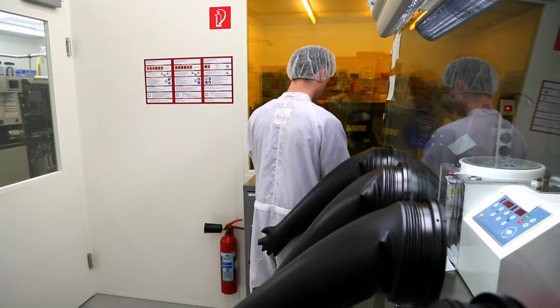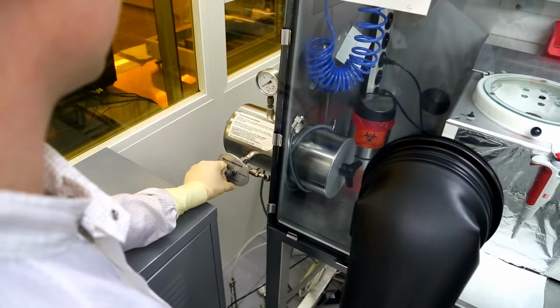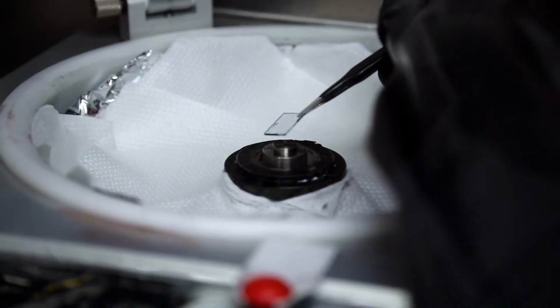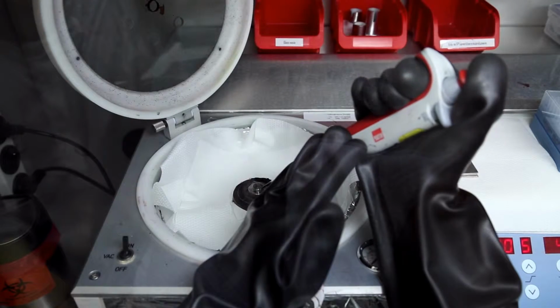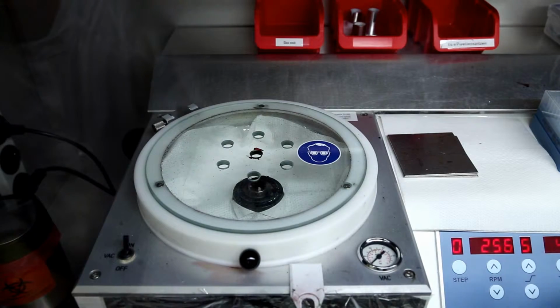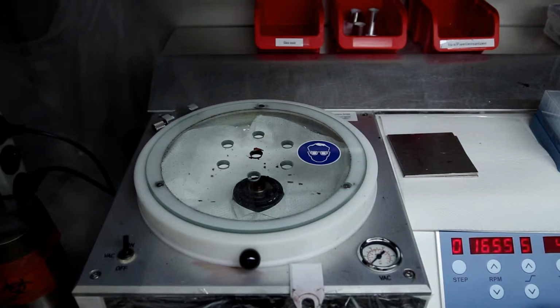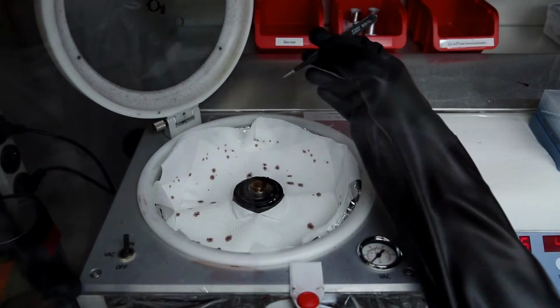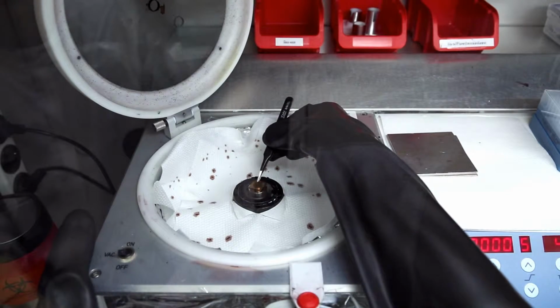The next step is the coating process, which is performed in another glove box. Once again, the vial and the glass plates must pass through an airlock and are then processed further in the nitrogen atmosphere. Daniel Baru dispenses the organic semiconductor onto the glass plate by means of spin coating. By rotating the plate at high speed, excess fluid is flung off the substrate. What remains is a thin plastic film. Spin coating is a procedure mainly used in research laboratories where work is performed on small-size substrates.